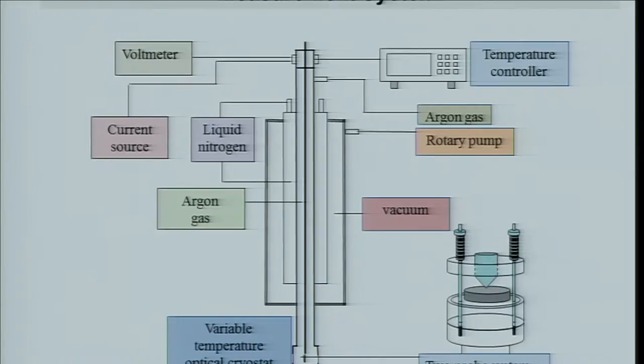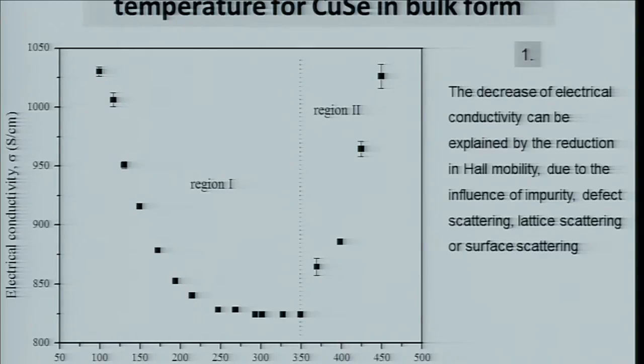But for us, we really want to look at the fundamental mechanism of the charge carriers inside the material. And to do this, we have developed what we call a low temperature two probe measurement system. Again, I have to give credit to my PhD student, who is now also an academician, Dr. Josephine, for designing and developing this particular system. And so this is the result that we got. We managed only to get down to the liquid nitrogen temperature, but our present system now is able to get down to 20 Kelvin.